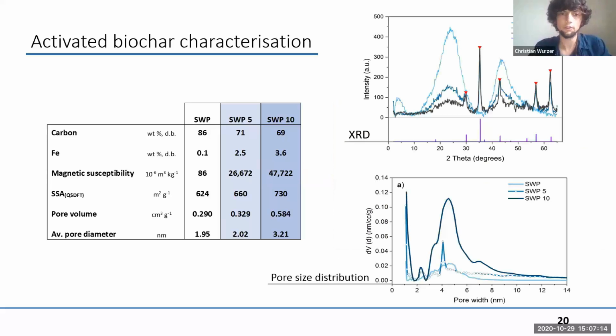We confirmed the magnetic susceptibility by X-ray diffraction, as you can see on the top right. The red peaks are for the ochre amended biochar samples, and the purple peaks at the bottom are reference patterns for magnetite, and we can see it adds up quite well. And we don't see a peak for metallic iron, so the goethite was successfully transformed to magnetite during the activation. And on the bottom, you see another important characteristic of the biochar, which is the pore size distribution.